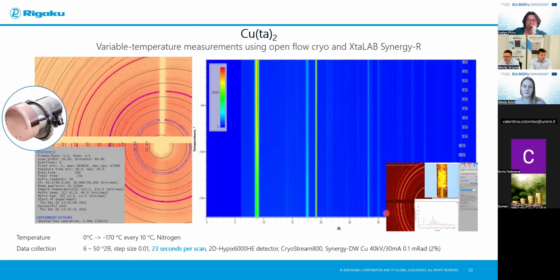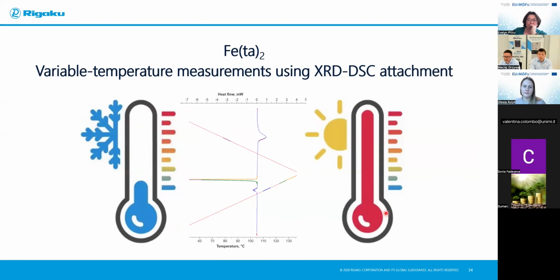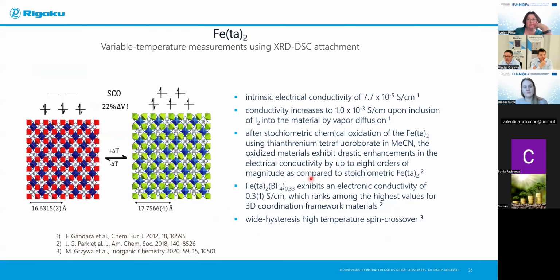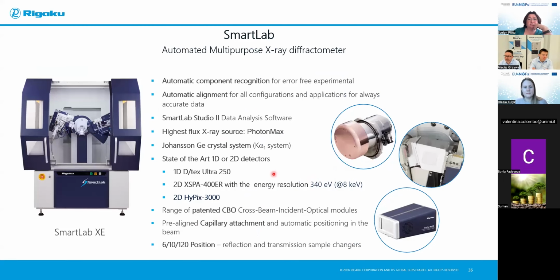So as I mentioned, 23 seconds per scan is not bad, but Maciej has another instrument to show you. Another example of variable temperature measurements is a case of iron triazolate. This compound is interesting due to its electrical conductivity as well as wide hysteresis, high temperature spin crossover. For data collection, in this case, we use a high-end SmartLab diffractometer, which can be equipped with a rotating anode.